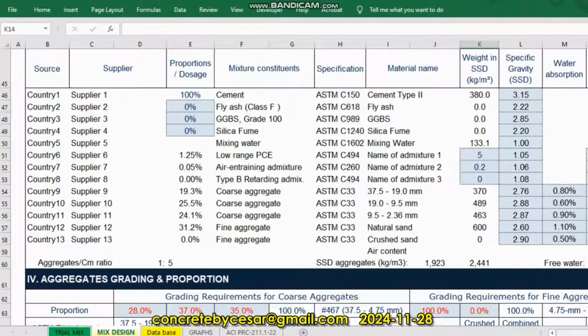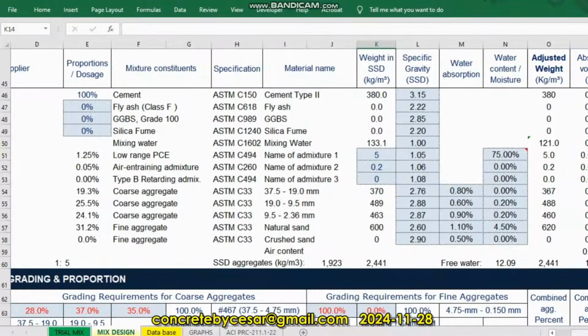So before I begin, let me show you what are the things you have to update before starting to do the mix design. First of all, you have to update the specific gravity. So you have to check your third-party test report or internal test report. Update also your water absorption for the aggregates, as well as the moisture for all aggregates, especially when we need to proceed for lab trial or actual production in the plant. And for the admixture, check your supplier also and update this percentage of water content in each admixture where you believe there is a water content.